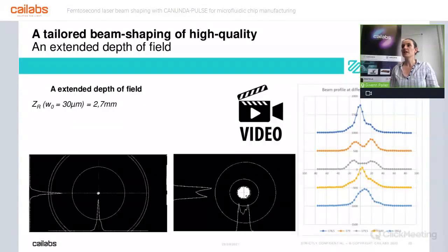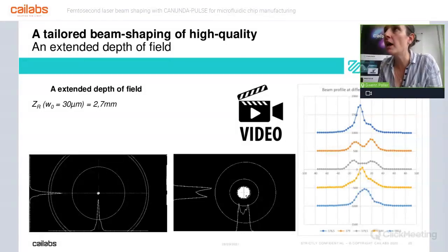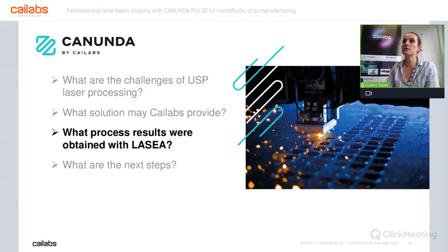All right. So the depth of field preservation is possible with MPLC because we managed to have the right intensity profile and the right phase profile in the processing plane. And having a plano phase, we managed to preserve the depth of field. So this is really unique to our technology as well. So this is it for the beam shaping capabilities and the optical result. And now we leave the floor to Mark to present the different process results that were obtained at LASEA.